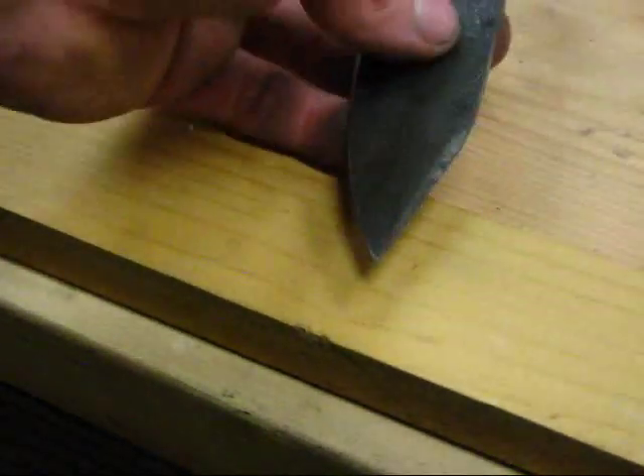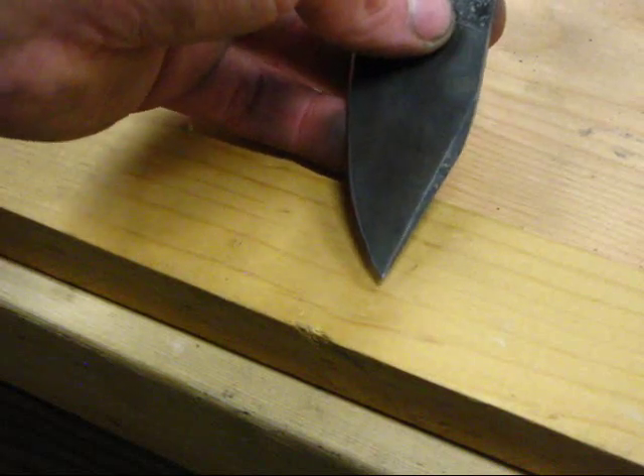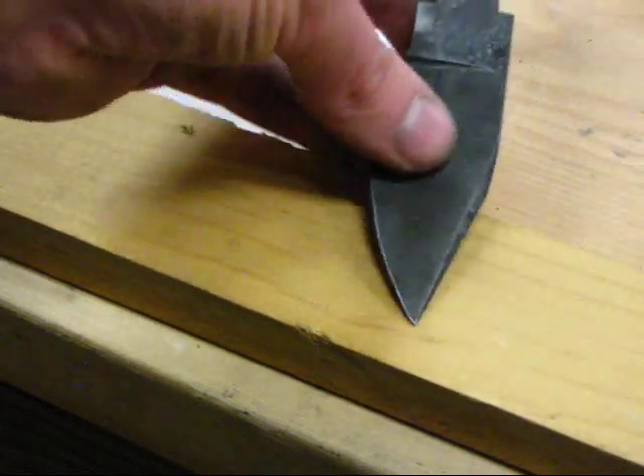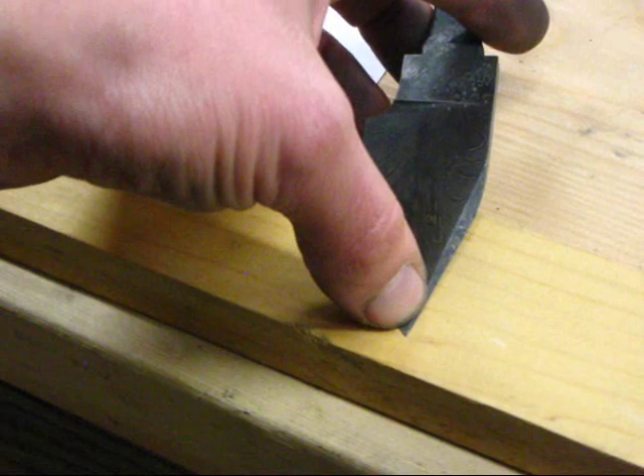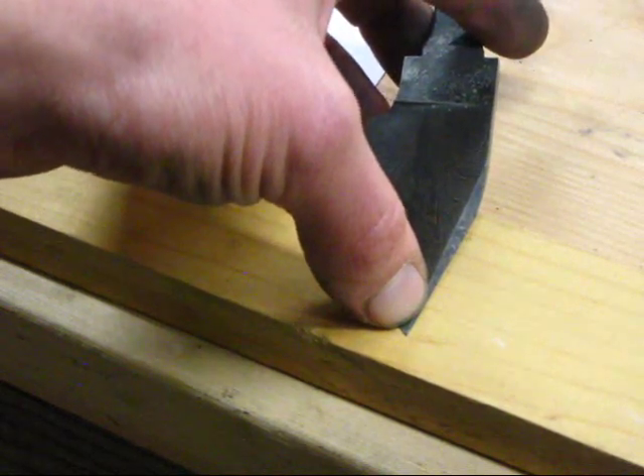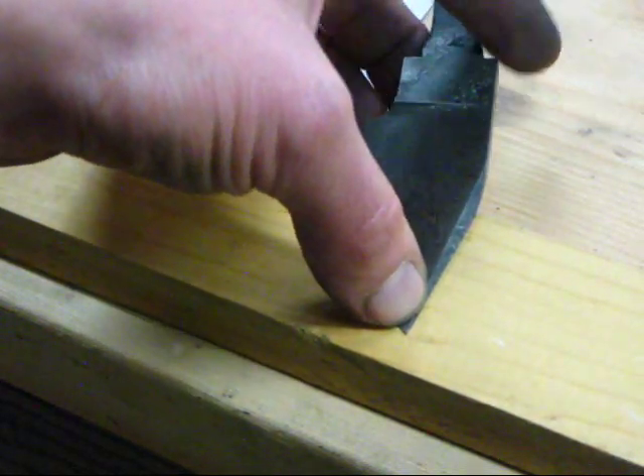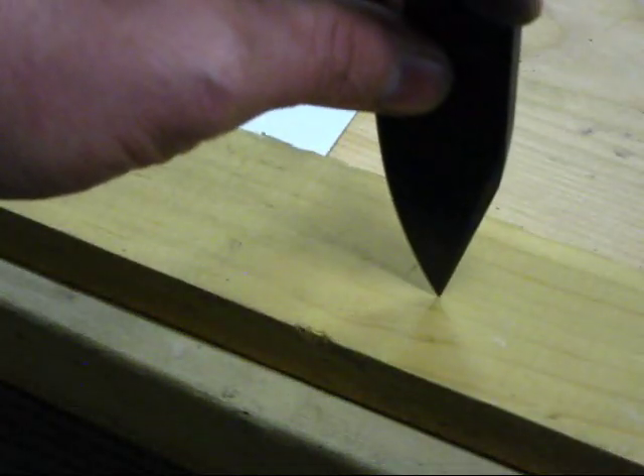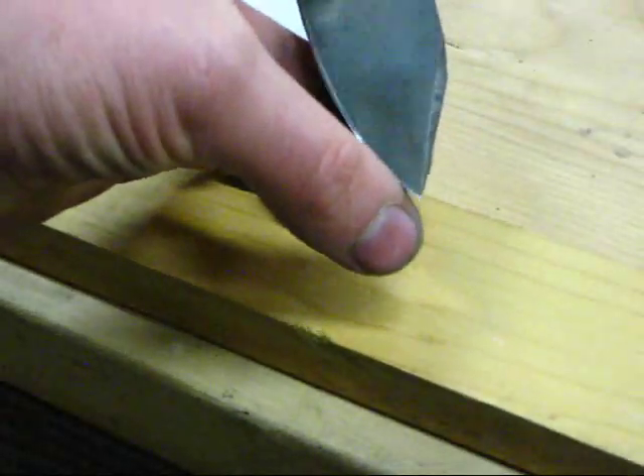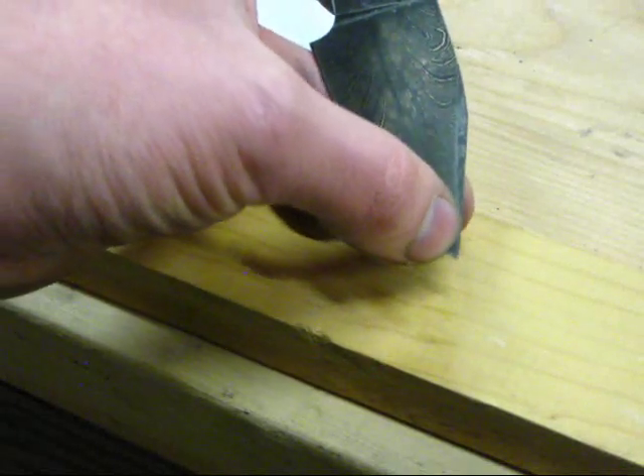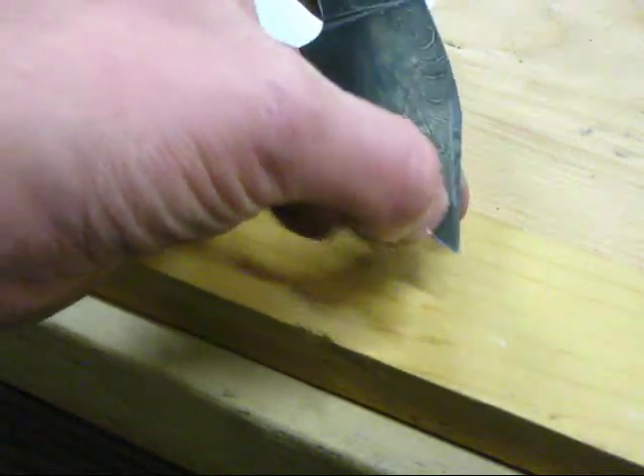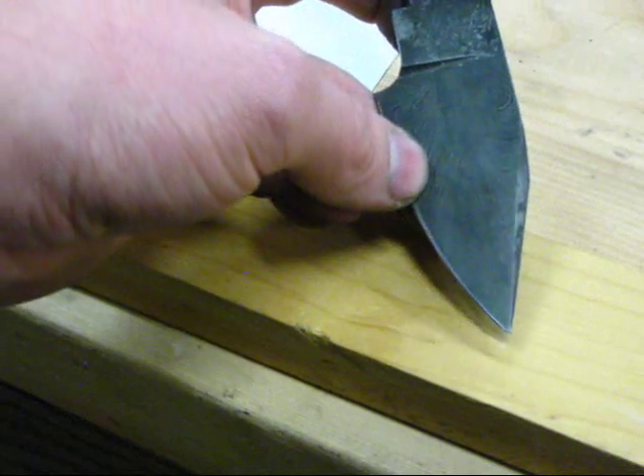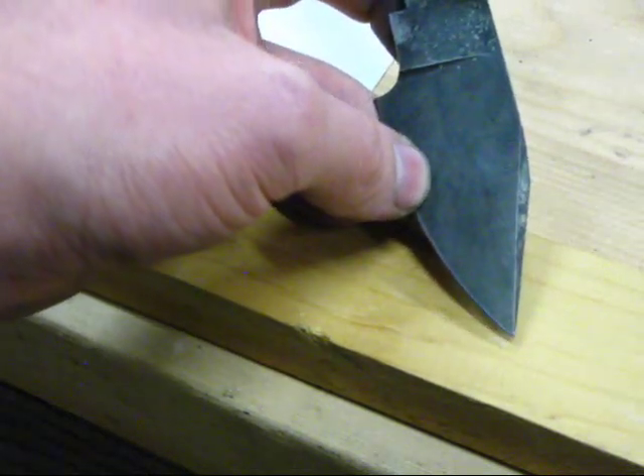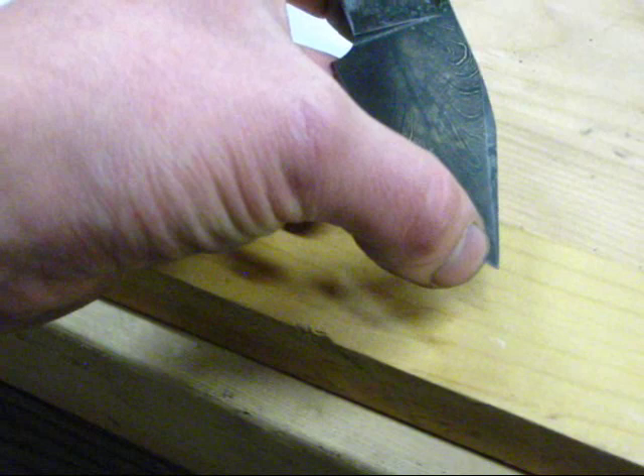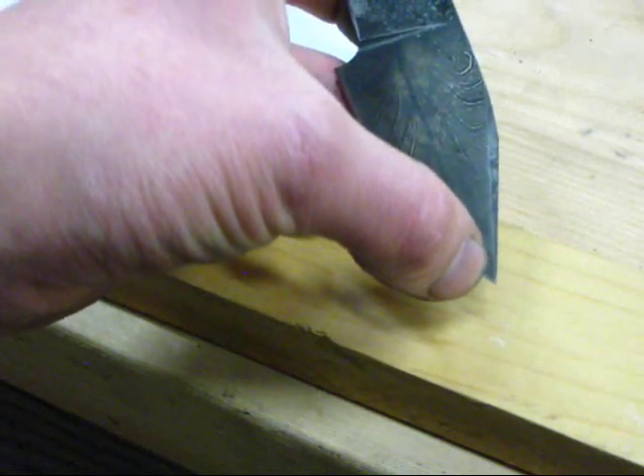If you stab this in and you fold the knife over and your tip breaks off, obviously your tip is too hard and you need to temper that area of the tip at a higher tempering temperature to impart more toughness in your tip. If you stab this knife into the board, you fold it over and the tip folds over and bends, that means that you've gotten your tip too hot and actually overheated it during the tempering process, and it's lost too much hardness, so now it is too weak and cannot maintain its nice point.